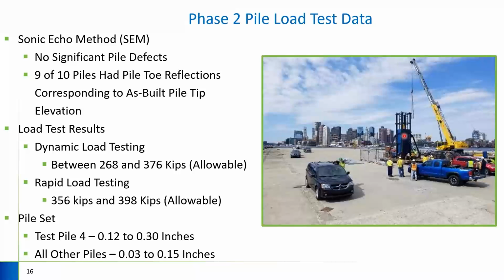So getting into the load test results themselves, for the piles with the dynamic load testing, we saw between about 270 and 375 kips of allowable load based upon the factor of safety of 2.5. And I'll get into on the next slide a little bit of why we didn't get the 300 kips in every pile. And then for the rapid load test, we were able to get 360 kips and almost 400 kips of load, which proved again that we had significant capacity out of these piles.